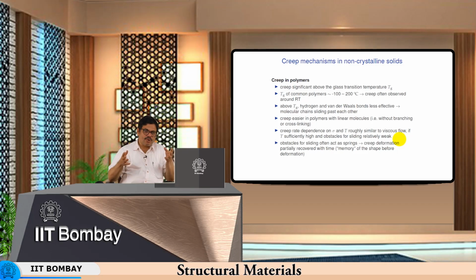Similarly, HDPE also will flow when the temperature is increased, but its viscosity will be relatively low because of the nature of the molecular chains. So, depending on the chemical nature of the molecular chains of every polymer, you will have different magnitudes of viscosity at a given temperature. So, the creep rate at a given temperature will depend upon the stress and the viscosity that the polymer is able to generate.